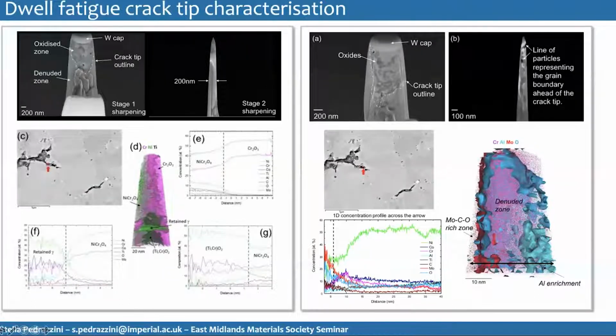And once it hit the first particle, the needle blew up. So I didn't really get the composition of the particles, but what I got is that the grain boundary is enriched in molybdenum, carbon, and oxygen. And there is a sort of gradient of molybdenum. So this side was the beginning of one of those particles at the grain boundary.